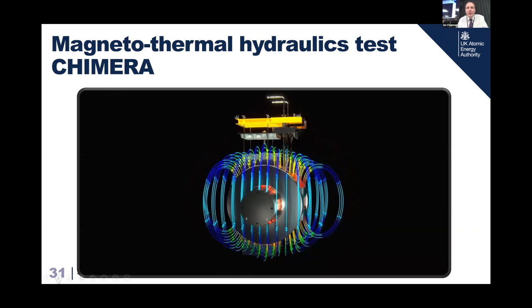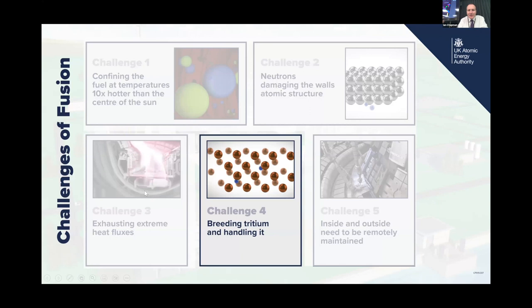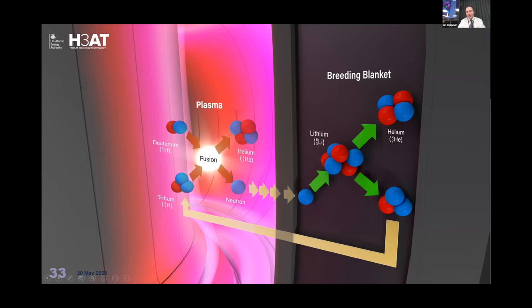Coming on to the fourth challenge, which is about tritium and how we handle it. So deuterium and tritium fuse, they produce helium and neutrons. The neutrons then pass through a blanket of lithium. And preferentially, we want lithium 6. Now, most lithium is lithium 7. Naturally it's about 7% lithium 6, 93% lithium 7. So we will have to enrich some of our lithium, maybe about 40% of it, up to lithium 6.